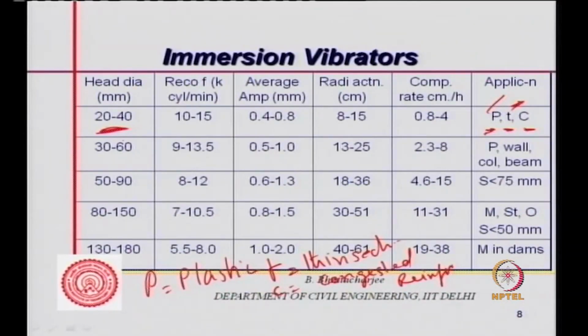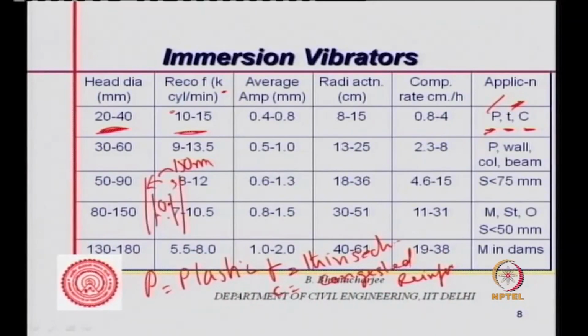For example, the web of a box section, a thin web of say 100 mm or 150 mm thickness, and you have a lot of reinforcement here, plus a pre-stressing cable passing through. So it's a thin section. Now the concrete has to be plastic, because if it's dry concrete, you will not be using this. The recommended frequency is given in kilocycles per minute, 10 to 15,000 kilocycles per minute.